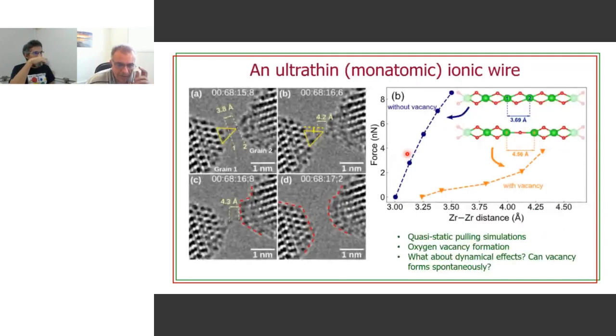Okay, so we also went ahead and tried to understand the very final stages of the sintering, which is, as I said, the formation of an ultra-thin ionic wire. If you go to the very last stages of breaking those two nanoparticles, you have very complex atomic rearrangements. Initially there is a 3.8 angstrom distance between two zirconium atoms. This is very much compatible with a stoichiometric model of an infinite ZrO2 ionic wire under tensile stress. But at some point, there's some atomic rearrangement so that this distance suddenly increases to 4.2 and 4.3 angstroms.